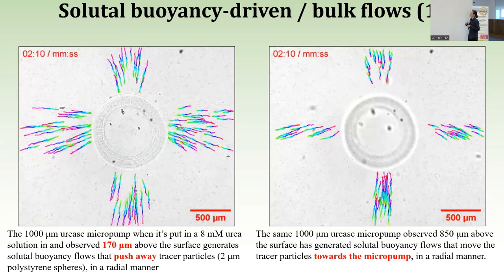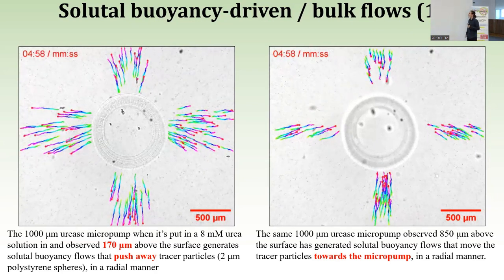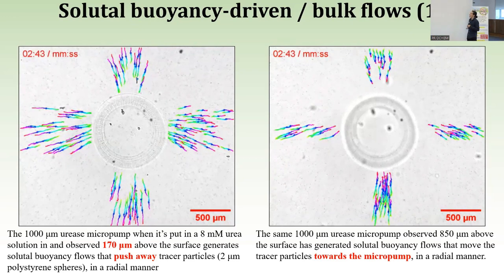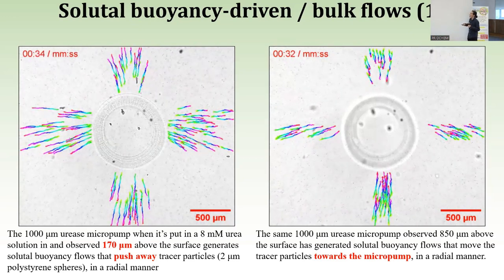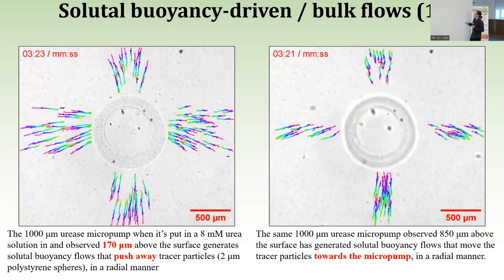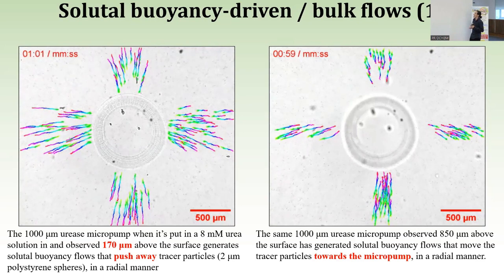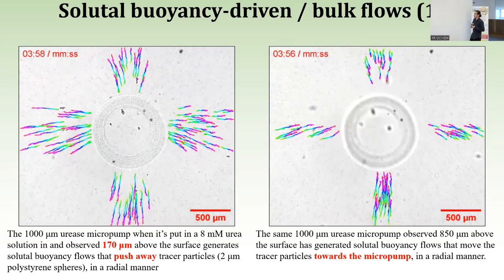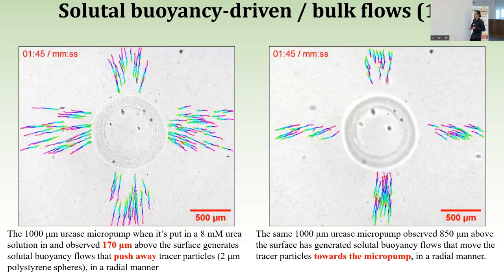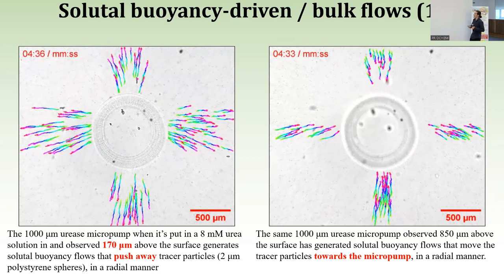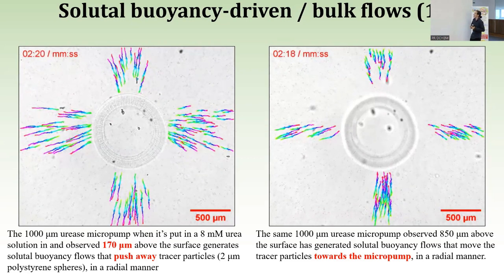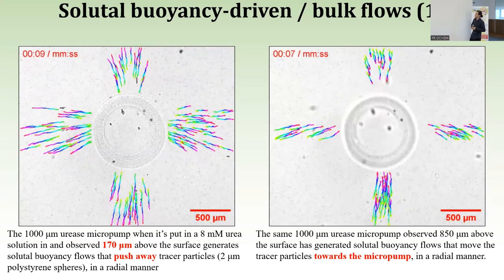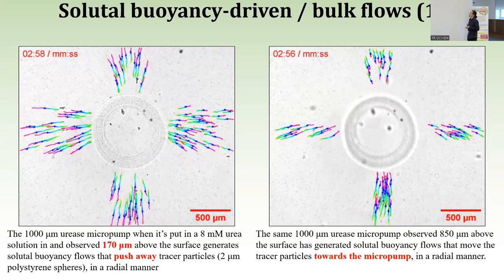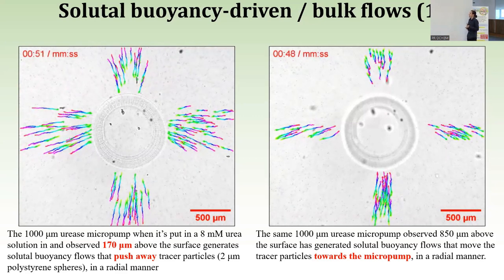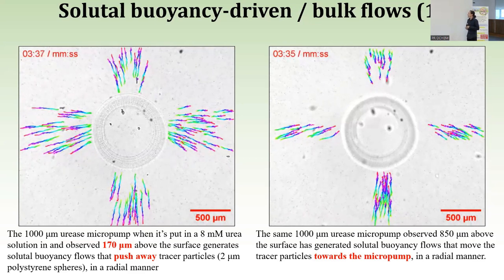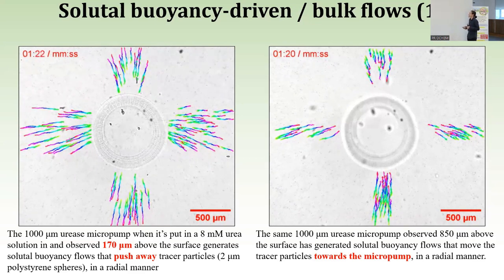It is notable that, first of all, we observe this with an optical microscope, and we set the focus of these experiments at 170 and 850 microns above these micropumps. With the help of these so-called tracer particles, which are 2 micron polystyrene spheres in this case, we observe the direction of these flows. At 170 microns above the surface, the tracer particles are being pushed away, and at 850, they are moving towards the micropump.